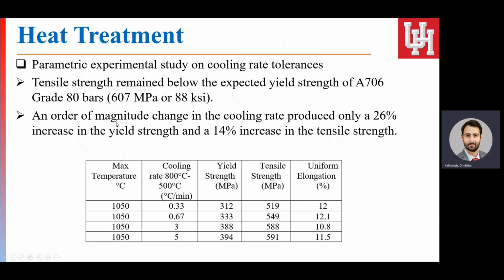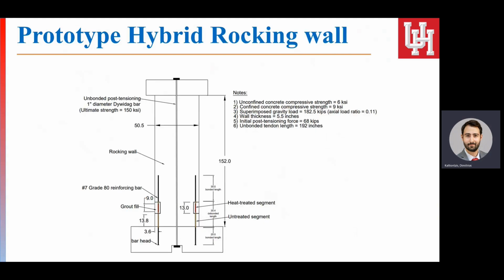And also, what we noticed is that the order of magnitude change in the cooling rate produced only a 26% increase in the yield strength and a 14% increase in the tensile strength. What that means is that our procedure is relatively versatile and can be applied in practice without any strict quality control of the cooling rates, which may be expected in many cases in practice. So this procedure provides relatively reliable results, even if there is low quality control in the shop.